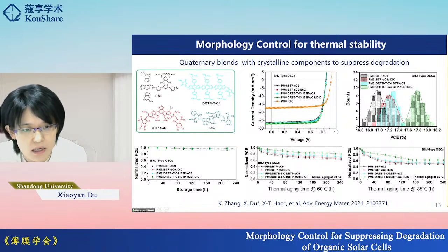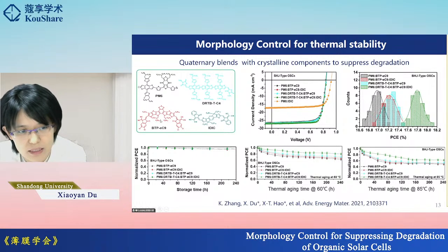In this work, we show that the devices based on this donor and this acceptor material indeed show very sensitive stability upon degradation under thermal annealing. Here is the room temperature device stability, and at 60 degrees it degrades very fast, and even faster at 85 degrees. Using ternary or quaternary blends, this degradation can be slightly suppressed.